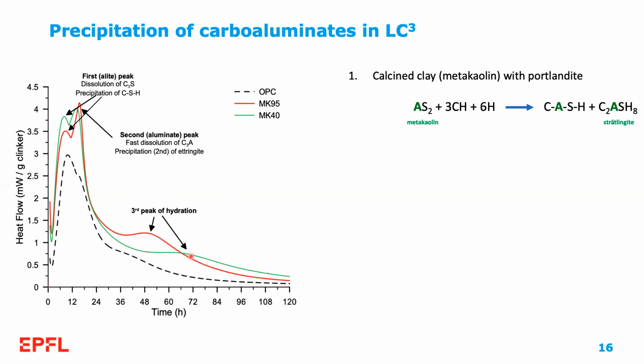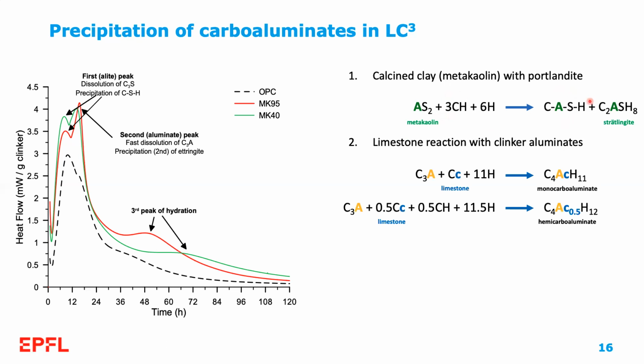And we have this third peak of hydration. And we wanted to understand which reaction was associated with this third peak of hydration, which appears enhanced in LC3 compared to what we see in Portland cement. And for this, we analyzed the different reactions happening in LC3 that involve metakaolin. So the first one that we see here is the classical pozzolanic reaction, where metakaolin reacts with portlandite and water to form CaSH. In addition, it's well known that limestone or calcium carbonate can react with the alumina from clinker, from C3A mainly, to form what we call carboaluminates, monocarboaluminate and hemicarboaluminate.